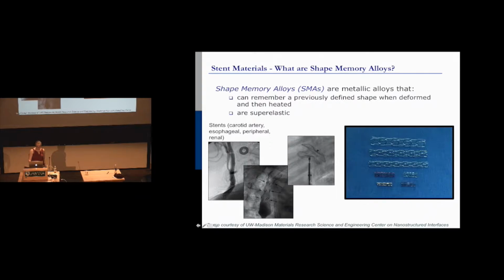And so what they did, you can see the heart wall right here, and this is one half of the heart patch, and this is the other, and it's basically just closing up the hole. So this is made up of this nickel titanium. And because you could take those two pieces, and you can see the catheter coming down here. So they pulled those two sides of the heart patch into the catheter. So you just had this very long wire. And they cut a 1-inch hole in her leg, and they wove it up through her femoral artery up into her heart. And then they basically deployed it inside her heart.